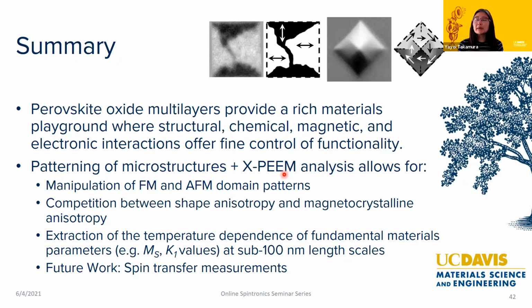If you want to know what magnetic state that region is in, Andreas Scholl, who created the PEEM3 microscope, always says you need to have 5 pixels in there. So the magnetic spatial resolution is always worse than the SEM spatial resolution. And that depends a lot on how conductive your sample is. One thing I didn't mention is that in the PEEM, in order to better capture all the electrons that come off the sample, we apply something like 20 kilovolts to the sample. That's fine if you have metallic magnetic materials, right? But these oxides are never very conductive, so we can never push that voltage as high. And so your spatial resolution for these complex oxides is worse.